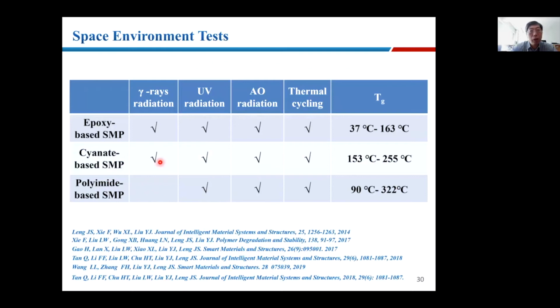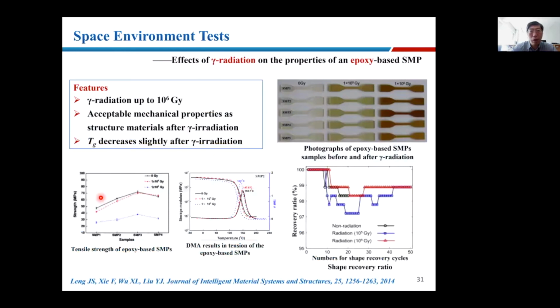So we've done a lot of tests, especially environmental tests, including gamma ray radiation, UV radiation, AO radiation, thermal cycling, and different temperatures, for the epoxy, cyanate ester, and polyimide shape memory polymers. I take one example, epoxy-based shape memory polymers. After certain doses of gamma radiation, you can see that after certain bending cycles, the recovery ratio, which is very important for shape memory polymer, can still keep more than 97%.